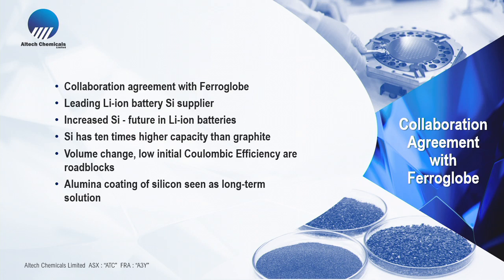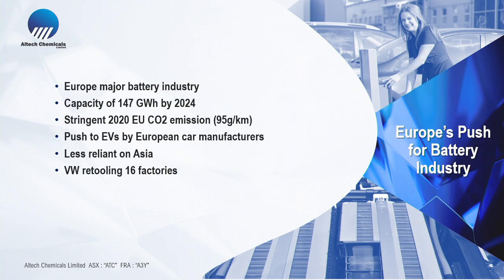But the problem is silicon expands about 300% in volume, and we don't think that you can get all silicon anodes, so graphite will always be there, and we think the proportion of silicon will be increased as you go through over the decades. So silicon is a very important development in the lithium-ion battery. Why are we focused in Europe? Essentially, Europe will be the big change in the lithium field.